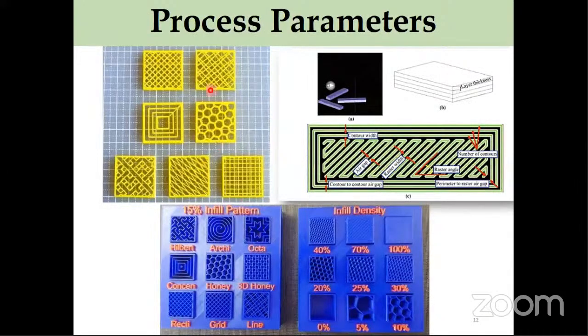So we were talking in our previous slide about different patterns. These are different infill patterns, how your material will be deposited. So this actually helps in weight saving also. And honeycomb structure, triangular, rectilinear. We have tried some of these in our work also. And infill density, say for example, 100% infill density, 70% infill density. Part orientation, what I was talking about, how you build this part. Layer thickness, what would be the thickness of each layer while you print it.